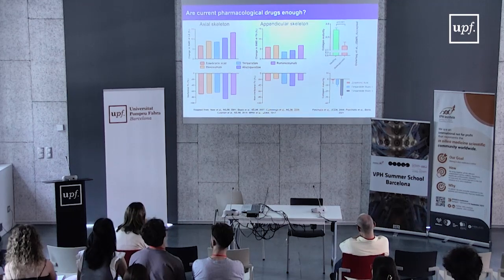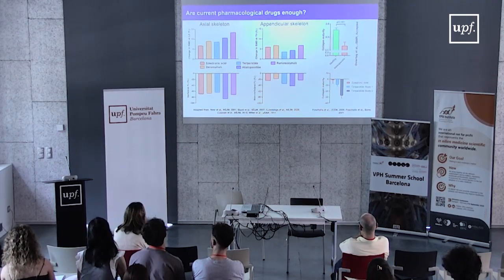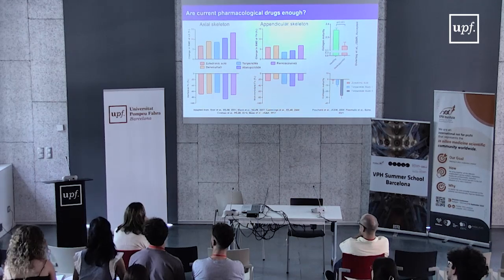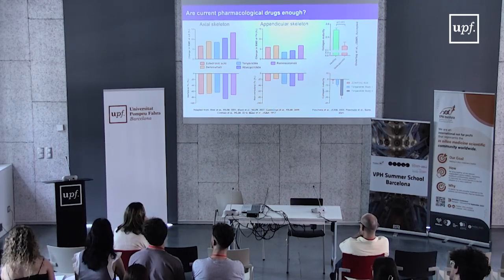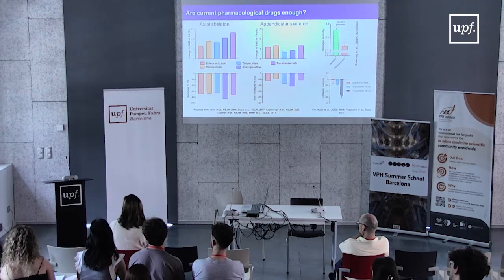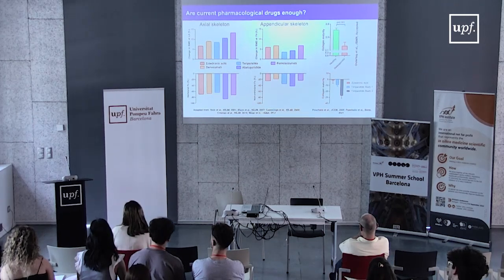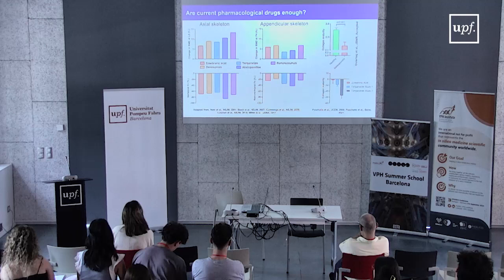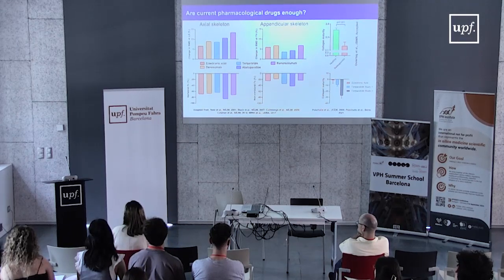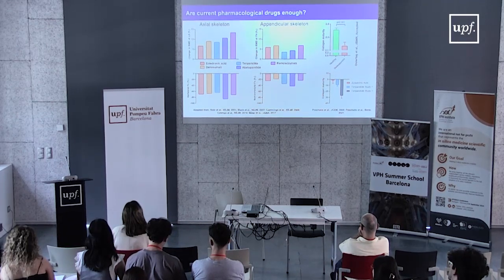And teriparatide and all anabolic agents are even more worrying because they will reduce even further the cross-linking which is compromised in osteoporosis. So you increase on one side the quantity of bone, but you reduce even further the quality of the bone matrix. And it's for that we really need, and there is a space for, new molecules that will target directly bone material properties to see if they would actually be better than the current therapies to reduce fracture in the patients at risk of developing a bone fracture.